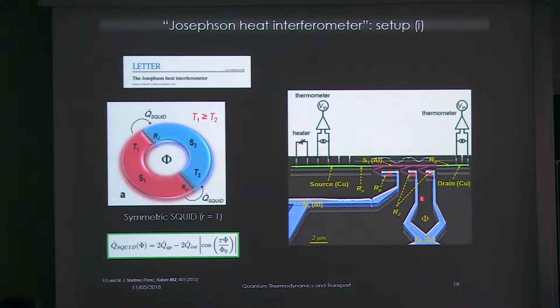So this will set up a phase-dependent part like this that, as a function of the flux, will start to oscillate. And so the amount of heat current transferred to the drain, that is the reading part of the circuit, will oscillate as a function of the phase. So it's very simple. For phase equal to 0, of course, this is minimized. So there is less flow from the red to the blue part, and so there will be a maximum in the electronic temperature here, and for half-integer values there will be a minimum.